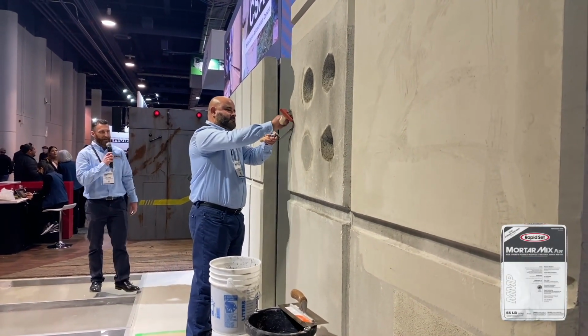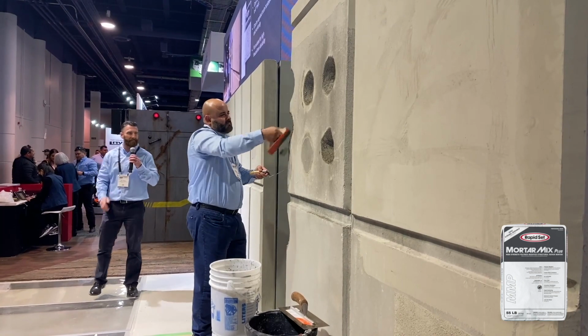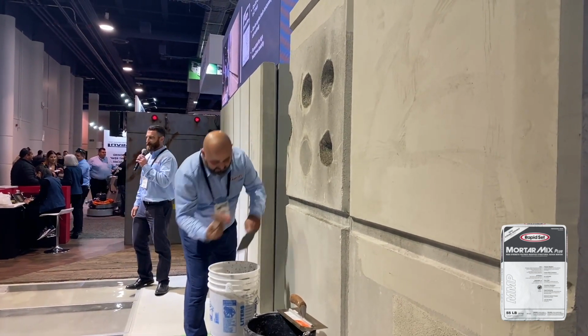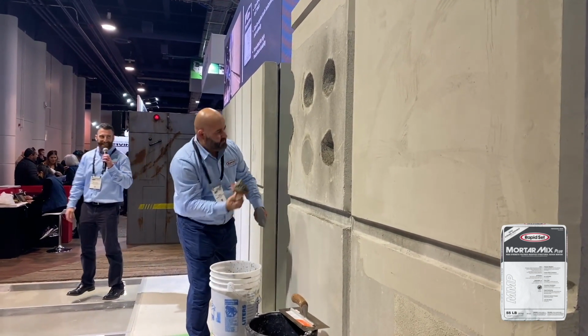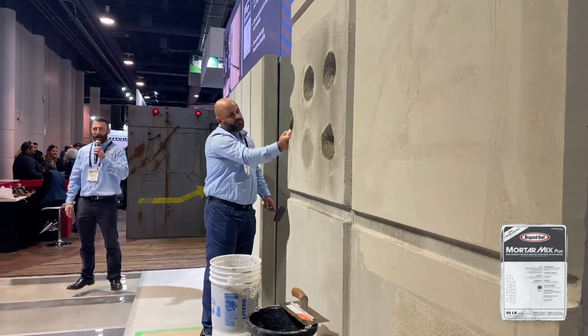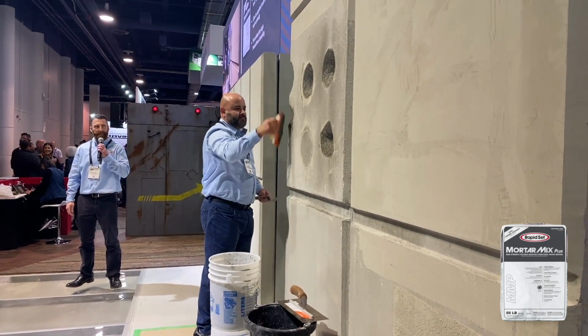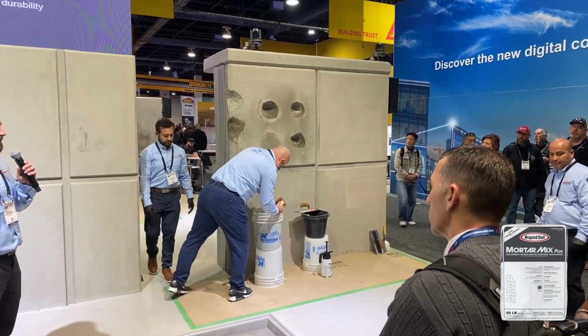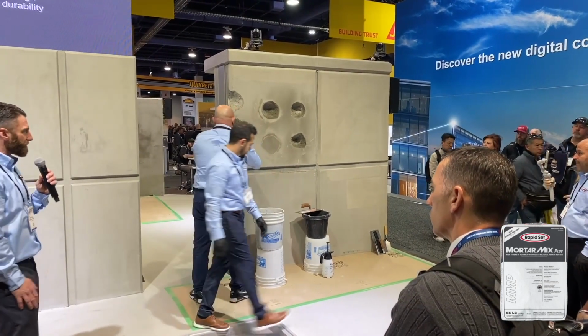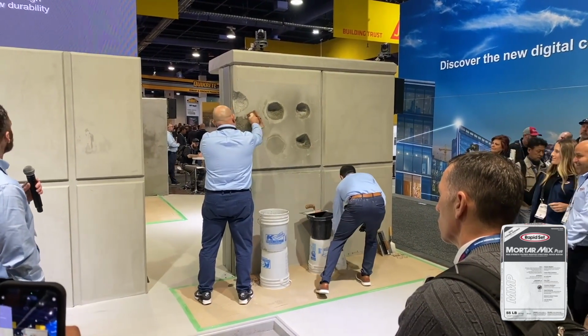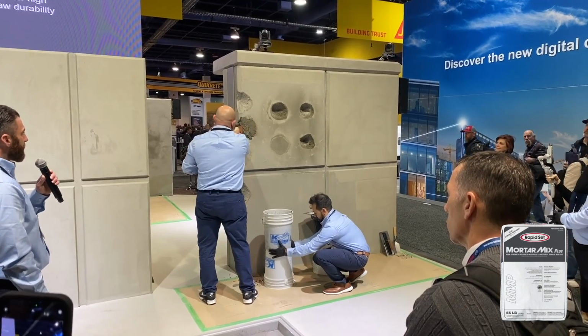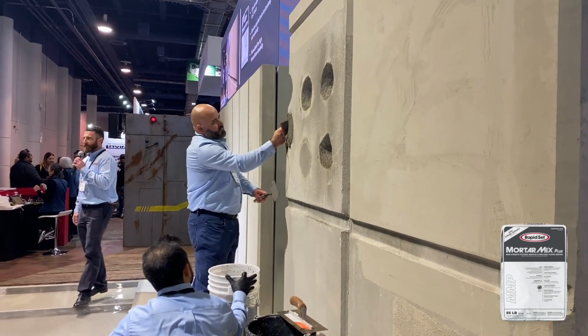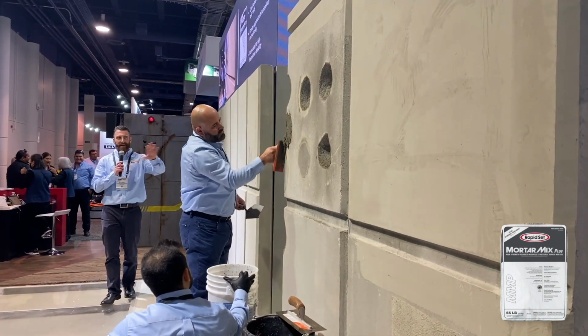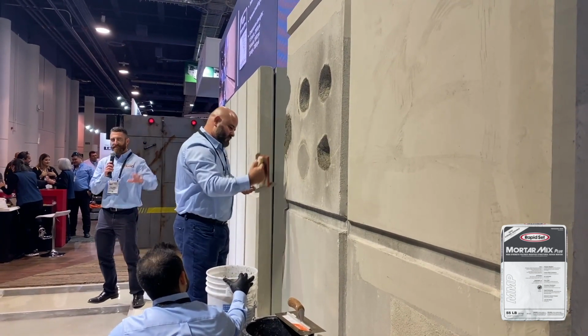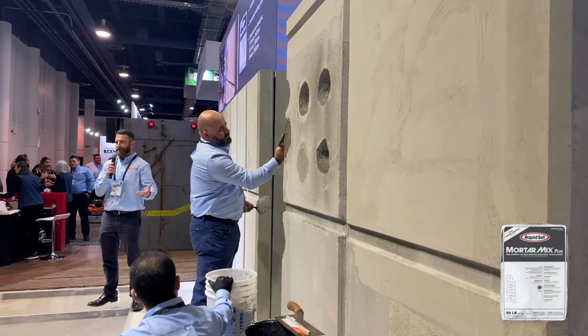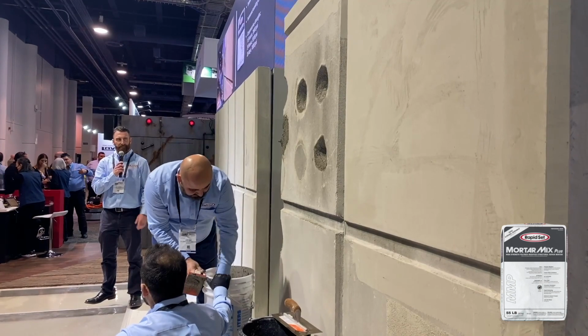So we're installing the Mortar Mix Plus. This product is designed to go from a 1/2 inch up to 6 inches deep. I mentioned it's polymer modified, and it includes the corrosion inhibitor, which protects the rebar from corrosion. If you're familiar with our mortar mix in the brown bag, this is kind of the next version of it. The first difference you'll notice is that it's pigmented gray to better match your existing concrete.